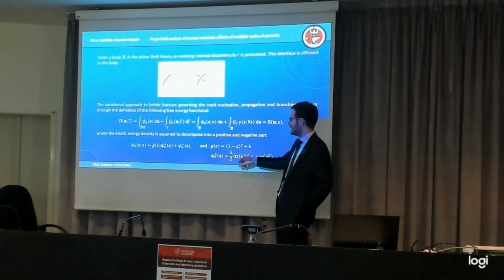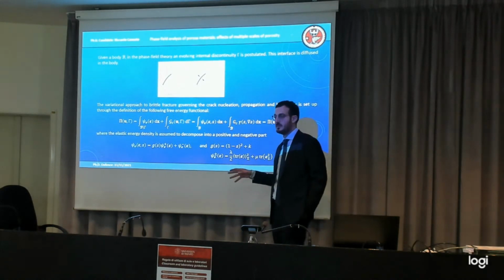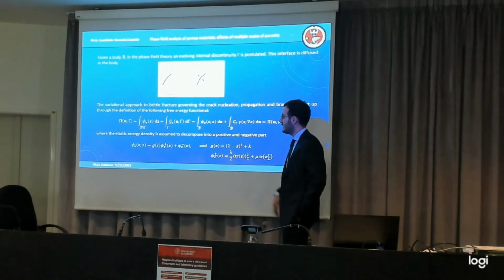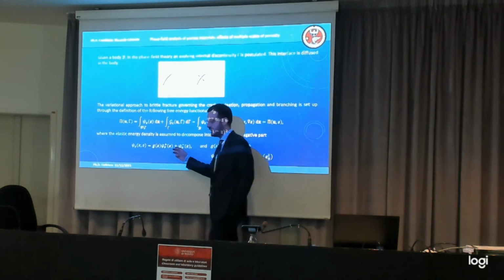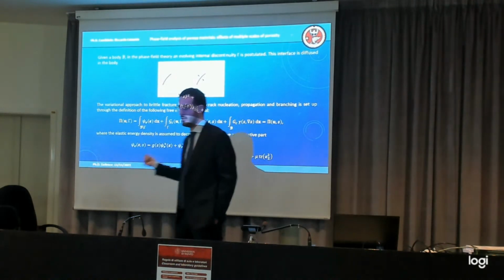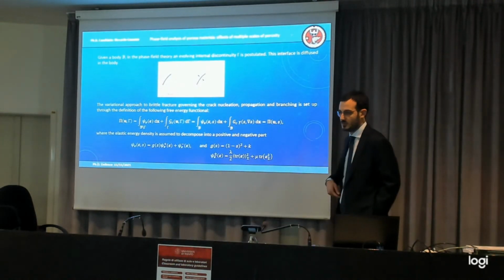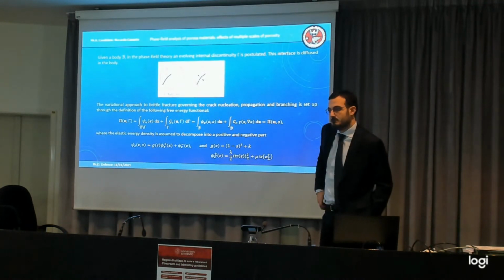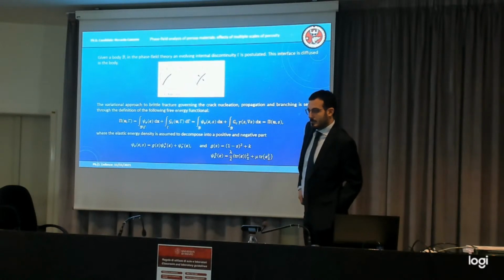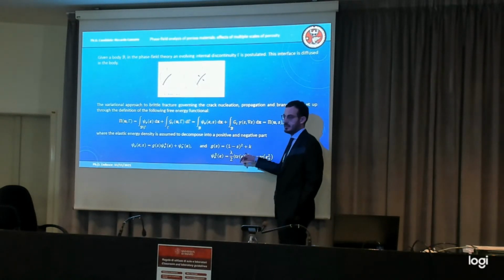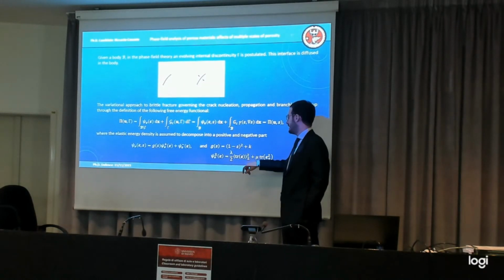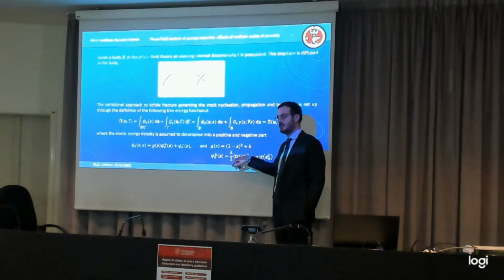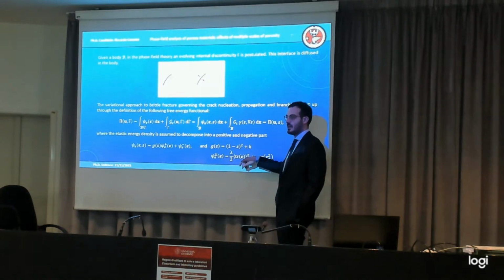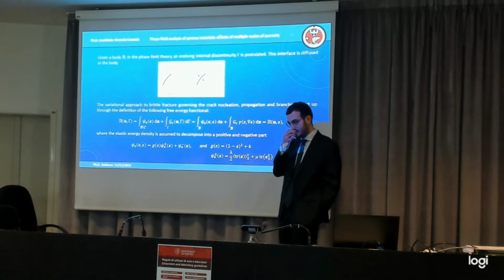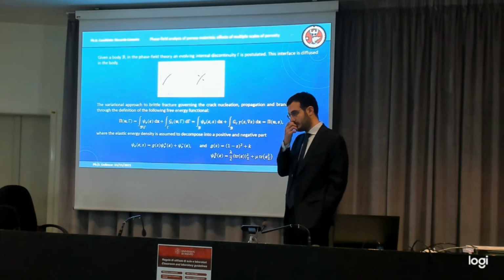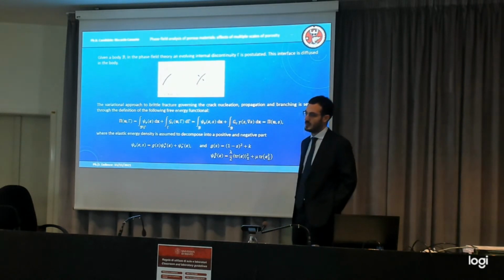Okay. This is the strain tensor, linear, small displacement strain tensor, and then you split up in this way. And the formulation, this was implemented first by Miehe. It's thermodynamically consistent. It still retains consistency from the thermodynamical point of view. So it's legit. But sorry, I don't understand. What does it mean, epsilon plus or minus? This is the Macaulay bracket. So you take the trace of the strain tensor, and for the positive part, it becomes 0 whenever this is negative, and otherwise it still retains the same. How do you decompose epsilon in a plus and minus? You do the eigenvalues split.